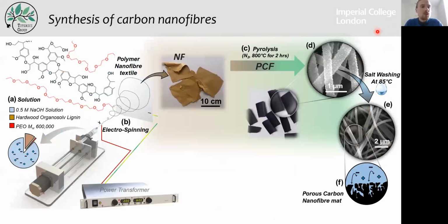So what we're doing in our group is using an organosolv lignin that's extracted not by the kraft process, but by an organosolv process. I can come back to explain that in more detail later. But basically, we dissolve this lignin into an NaOH solution of relatively low concentration. We add a bit of polyethylene oxide to facilitate the electrospinning, as it will align the lignin branches and facilitate the extrusion of the Taylor cone. Here we have a power transformer that puts this metal collector, a metal foil, at ground level, and here at 20 kilovolts, and it will pull out the drops and start creating a jet of fiber. Now the solvent will evaporate, and what we obtain is a mat of carbon nanofibers, approximately 500 nanometers thick.